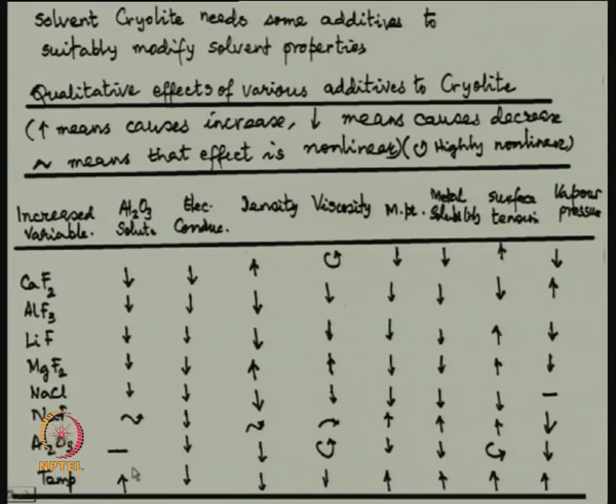So, while it may be necessary to add other solutes for various reasons that we will see, all these will decrease solubility of Al2O3 that you want to dissolve in the solute. What will happen to electrical conductivity? Calcium fluoride will decrease it, aluminum fluoride will decrease, lithium fluoride will decrease that, magnesium fluoride will decrease. All of them will decrease electrical conductivity. Some will increase density, some will decrease density. You can easily say that if you add something like sodium fluoride, which is a very light molecule, then it will decrease, but some others will increase.